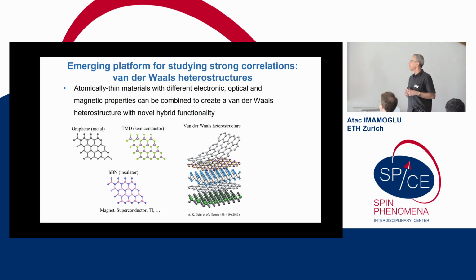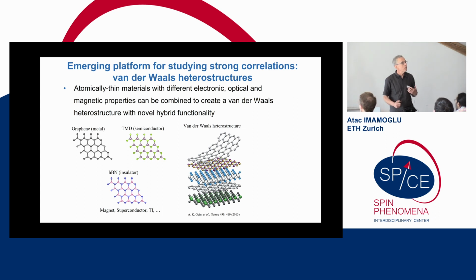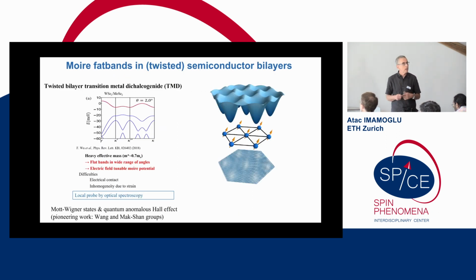mentioned, and follow up on the use of van der Waals materials for studying strong correlations. As many of you know, this is a big field, and I'm just going to address a teeny tiny corner of it. But again, as background, what really brings the new ability is the fact that you can take monolayers or bilayers of very different materials with very different functionality and put them into a heterostructure. Particularly if you do so when bringing together two layers with a slightly different lattice constant, or if they have the same lattice constant, by bringing in a small twist angle, then you can introduce a moire potential, a superlattice potential that modifies the electronic bands dramatically.